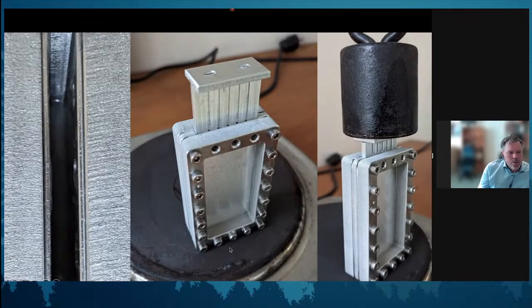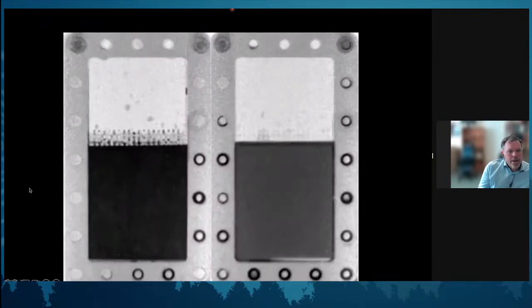And then by using an IR camera, we could actually see that the heating of the aluminum is very, very quick. So this was the only heating we had. Talking about understanding the load you have to the system, there is no need for calibration. It's just a weight. And this piston just makes sure that the sheet that is put inside, so this is looking from the side, actually doesn't move. So the final experiment looks like this.